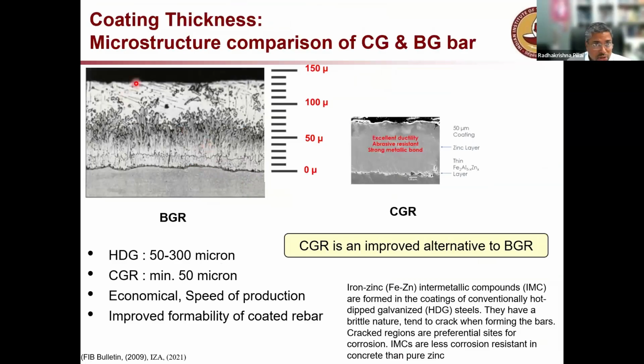Or before that, I'll talk about this. This is the galvanized steel on the left side, which is known for its corrosion resistance and all that. But unfortunately, it is not much used in the market because of cost factors. It's because of this thick galvanized zinc layer which you have here. As you see here, this is the steel part in a batch galvanized rebar, BGR. You can see steel here, and then this is the galvanized coating or the zinc layer, a mixture of zinc and iron. Now, the point here is this is very costly.